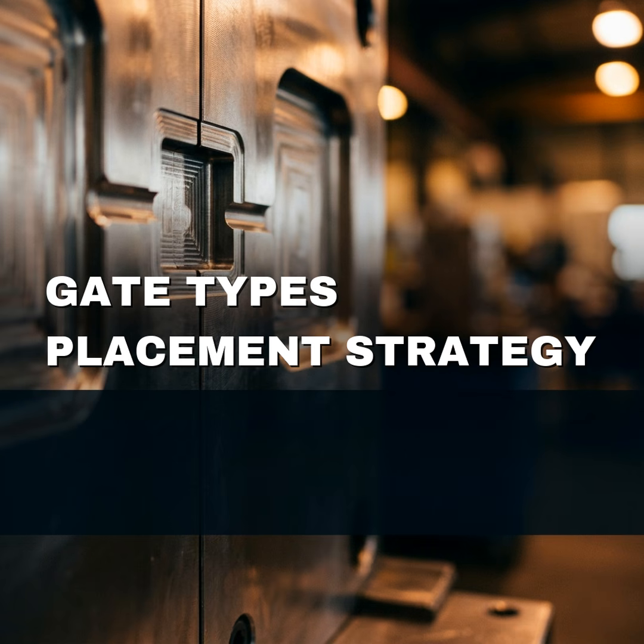Yeah, defects happen. One of the most common is a gate vestige or gate mark, basically, a visible leftover from the gate. That's usually caused by a large gate size, improper gate shape, or bad location. The solution is to use a smaller gate, change its shape, or optimize the location to make the mark less visible. Sometimes it's insufficient gate filling, so you adjust injection pressure, speed, or temperature.